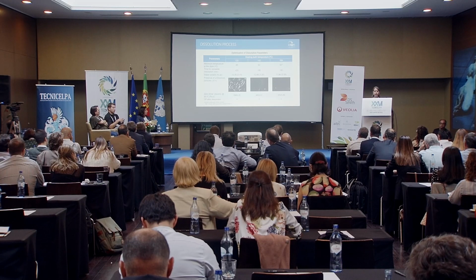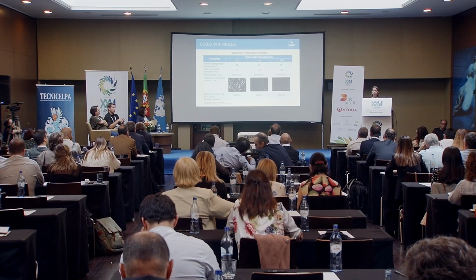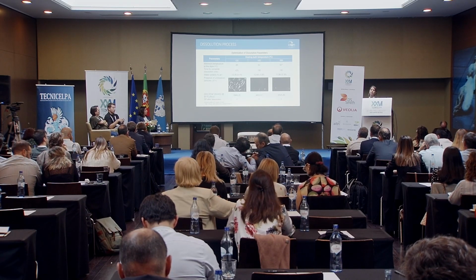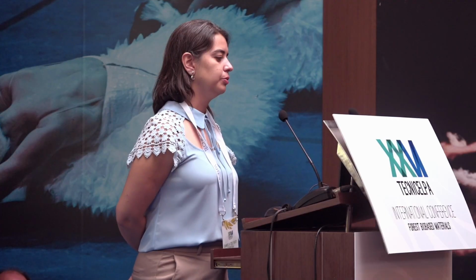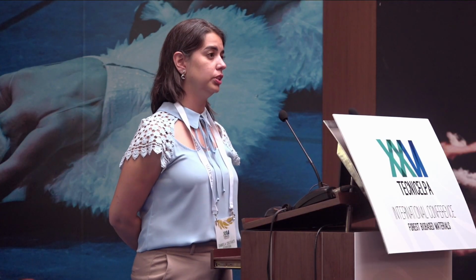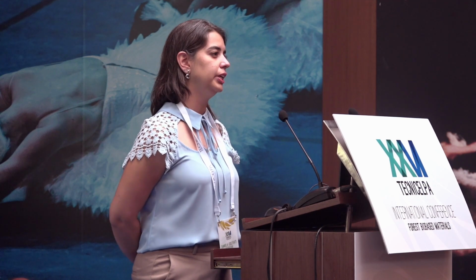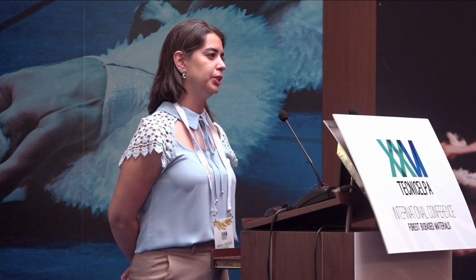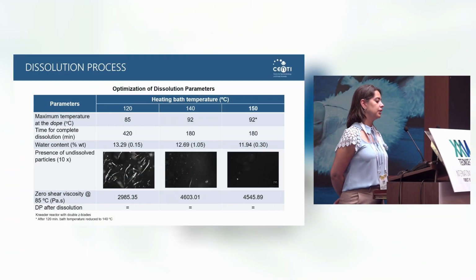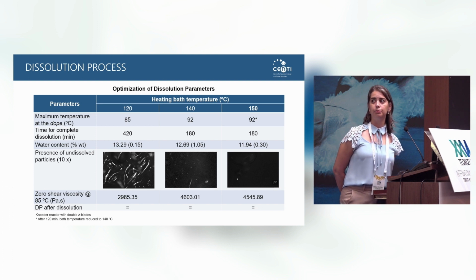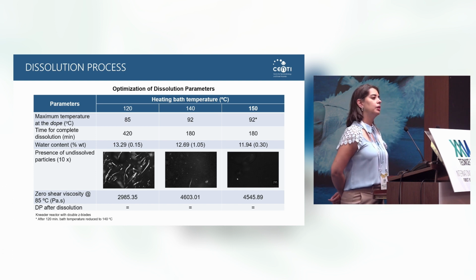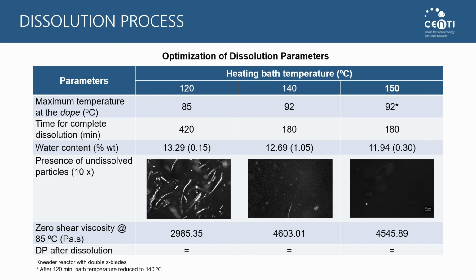The control parameter of the dope is the water content, measured by refractive index. We saw that in all 3 conditions we were in the range we wanted, between 9 and 12. But looking at the optical microscope, we see that at the lowest temperature, we have a lot of cellulose fibers that were not dissolved. At 140 and 150, it's okay, it was clearly dissolved.